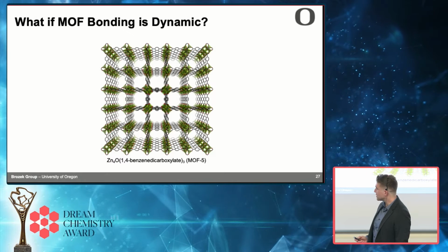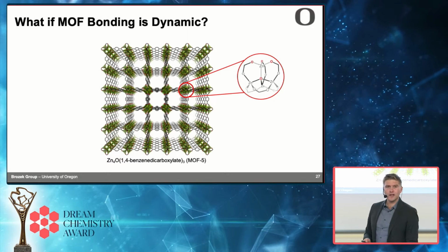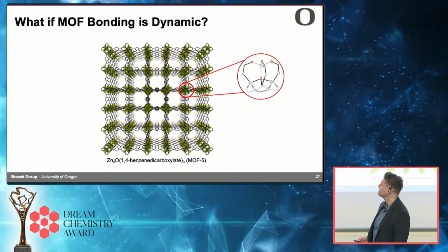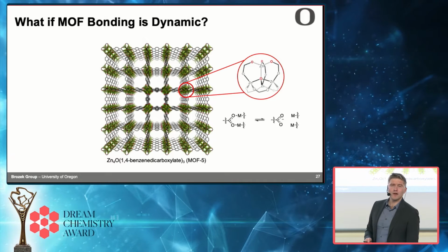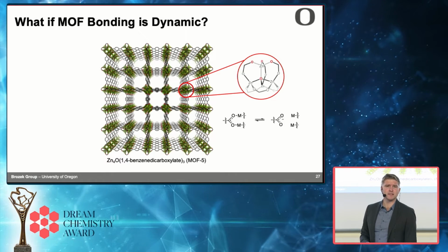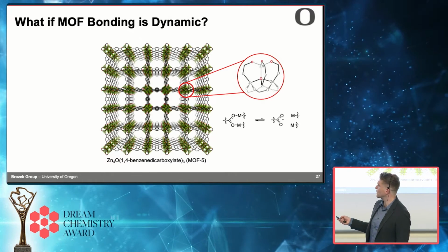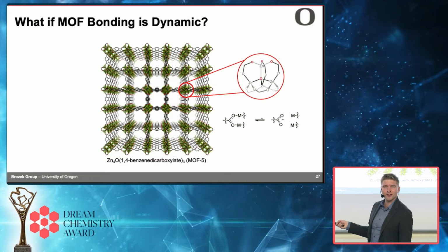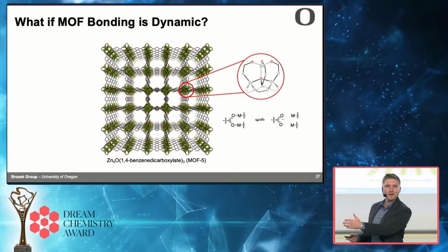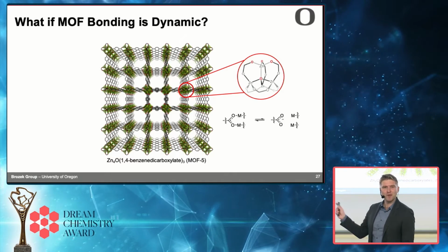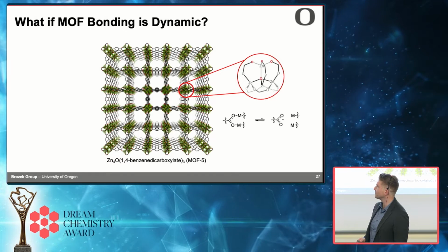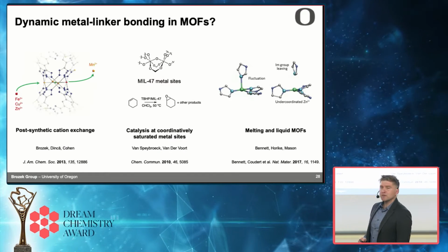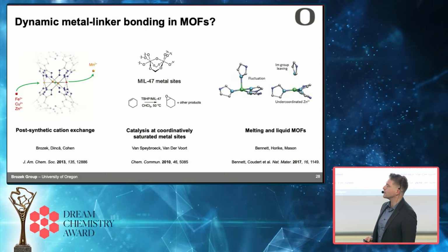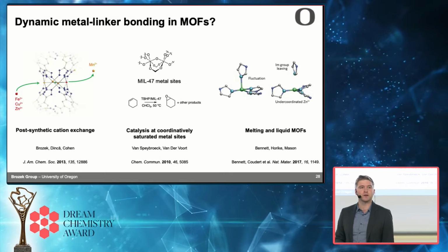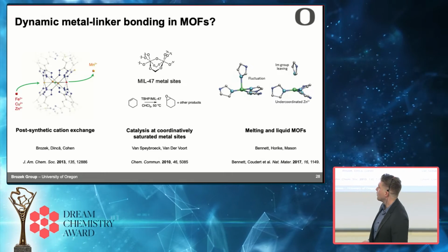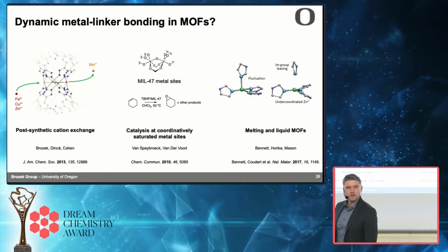But as coordination chemists, you can take a look at what those metal ligand bonds look like. And you know that metal carboxylate bonds are known to be really dynamic. As molecules, they constantly exist in this fluxional bonding broken equilibrium. Okay? In fact, people can measure that equilibrium. Well, this would be really important for this field because it would explain a lot of really bizarre behavior for MOFs.